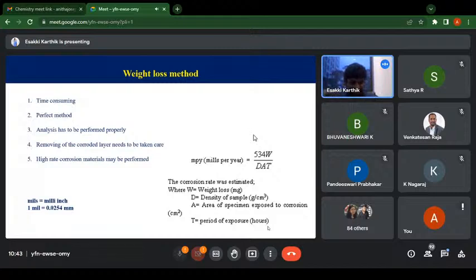But the analysis has to be performed properly. It means you should not remove the layer of the metal surface. When you remove the layer of the metal surface, what happens? We will end up with the wrong result for the real corrosion rate. And suppose corrosion is happening at a high rate, then only you can measure. At least it will take its own time, 2-3 months. If it is a high rate, at least after 1 or 2 months, you can measure the corrosion rate.